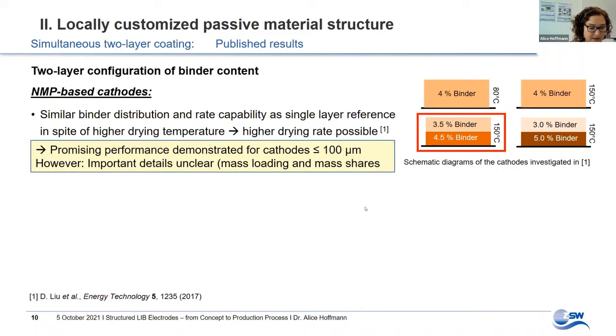However, from this study, important details are unclear. The cathode slurries were fed separately by two pumps at the desired flow rate through each die to reach equal wet film thicknesses. And the casting was only tuned to similar thicknesses after drying. However, the solid contents and active material contents of the slurries were different. And for this, the active mass loading and the share of active mass in the individual layers is unclear.